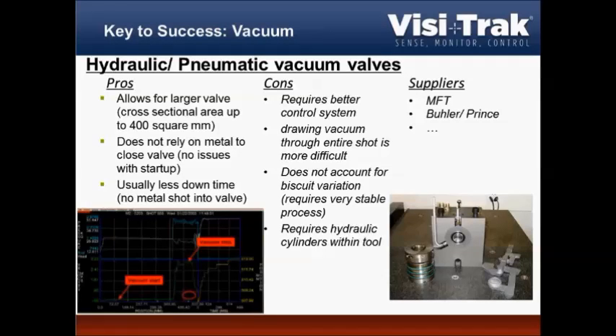At BDW, we of course had the MFT system, because MFT is minimum fill time, that was invented by the Turner family, the former owners of BDW. That allows for a much larger cross-sectional area. It does not rely on the metal front to close the valve, so you won't have metal shooting into it as long as your machine is properly under control and your control system tells the vacuum valve when to close exactly. So if you do it right, you will have a lot less downtime. But as I said, it requires a much better control system, and it's more challenging to draw vacuum through the entire fast shot. And it does not account for biscuit size variation.